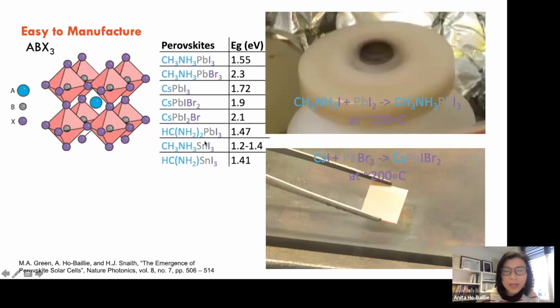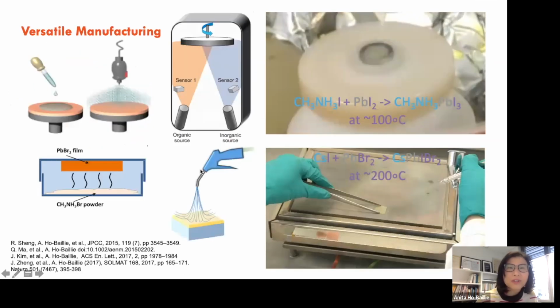Okay, so it is also very versatile in terms of the deposition method. You can spin it, you can spray it, you can even evaporate it in powder form. So heat it up and the powder will sort of sublime onto the substrate. You can do it in atmosphere or in vacuum, or you can even just put it on the substrate and then use a nitrogen gun, so this is air, to just blow it to evaporate all the solvent out and induce it to sort of a supersaturation for that crystallization to happen.